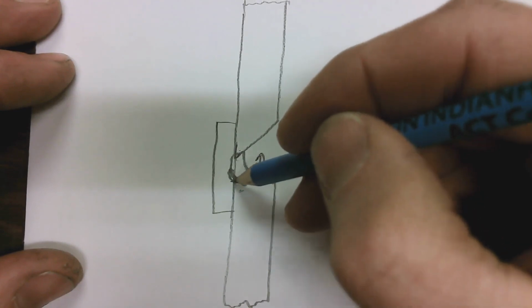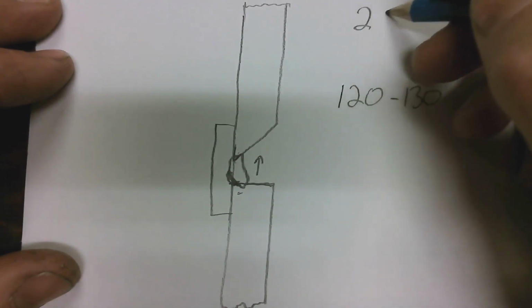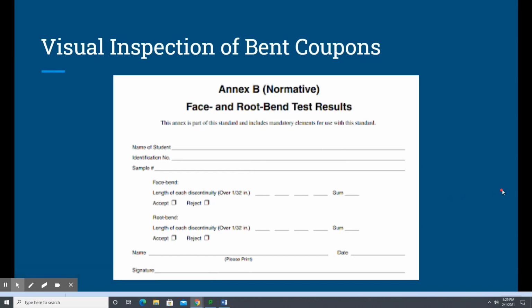So got to make sure they run nice and hot on that root pass. I usually run somewhere between 120 and 130 on this 2G. Okay, again, this is a 2G test, so it's a horizontal weld, horizontal V-groove. On the vertical ups on the 3Gs, okay, I'll run those a little bit colder because heat rises, so I'll run those typically 105 to 110, maybe 115. Kind of depends on if I'm running stringers or weaves, but yeah, definitely got to run a little hotter on the horizontal welds there.